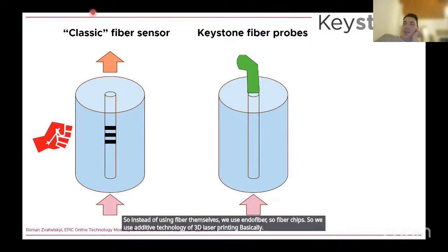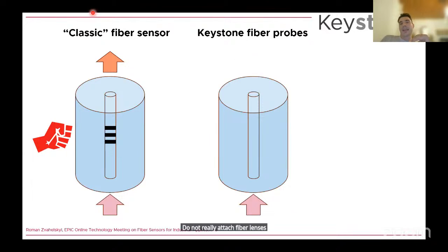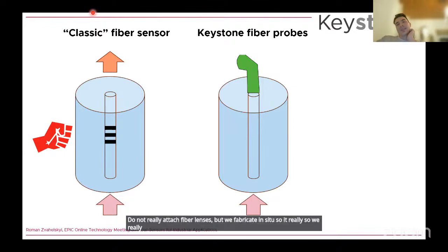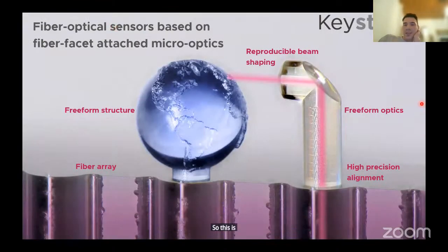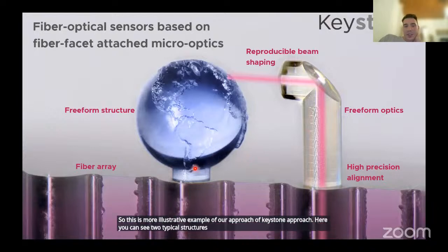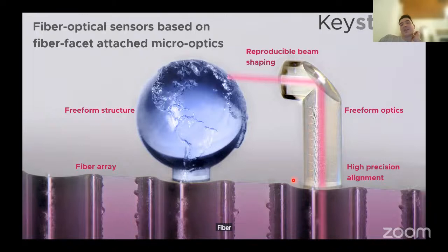We also use femtosecond lasers, but instead of inscription, such as the Alphanov company does, we do additive manufacturing of polymer lenses. And we do not really attach lenses to the fiber, but we fabricate them in situ. We detect the cores of fibers and fabricate polymer micro-optics in situ and use them as sensing devices. This is a more illustrative example of the Keystone approach. Here you can see two typical structures printed by Keystone Photonics. This is a cross section of a fiber array, and the first structure is a freeform structure. This is a globe, and the second fiber was used for printing a periscope lens that focuses light into this globe.